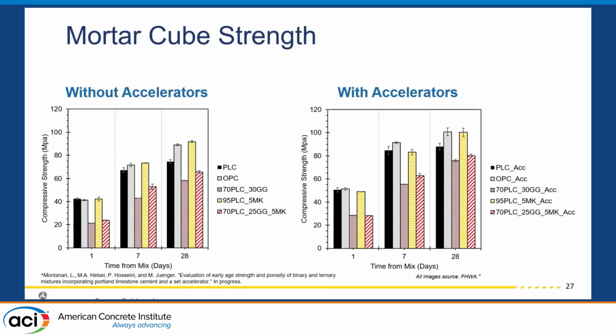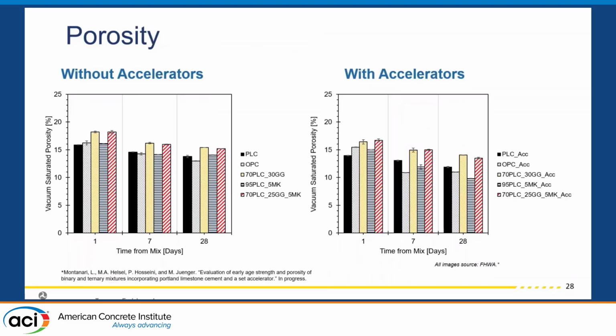Looking at some mortar cube strengths, you can see very similar mortar cube strengths at 1 and 7 days for our OPC and our PLC. It's a little bit lower for our PLC at 28 days, but by that time, you've probably got what you needed from your high early strength mix, right? You wanted that really rapid time frame. And then looking at porosity, without accelerators, our PLC and our OPC do a really good job. They're right next to each other, sitting there hanging out. And then with accelerators, at 1 day, you can see that our porosity is very similar.